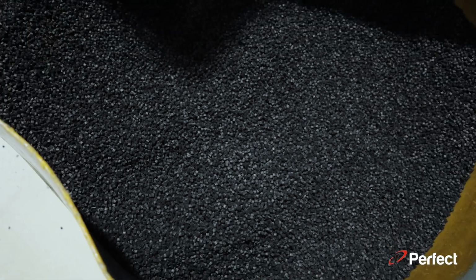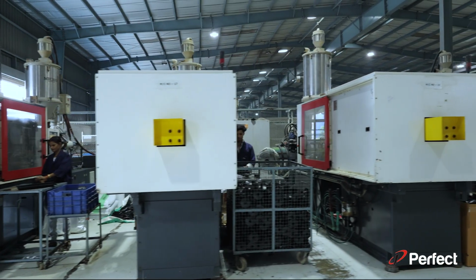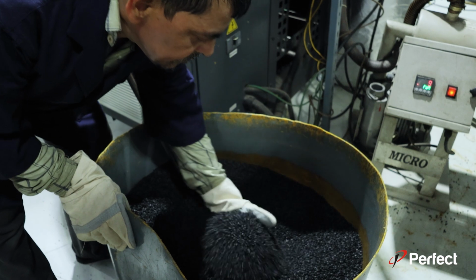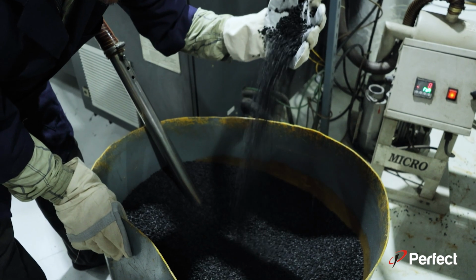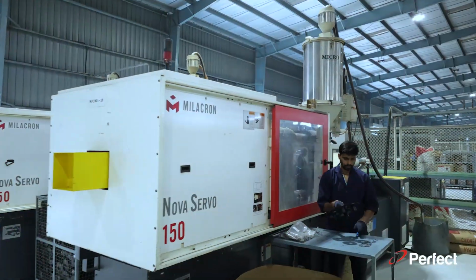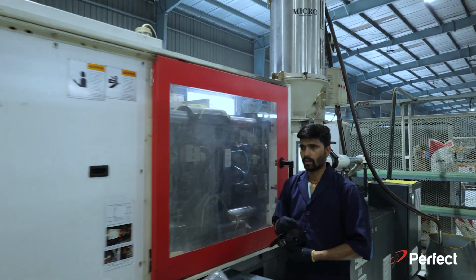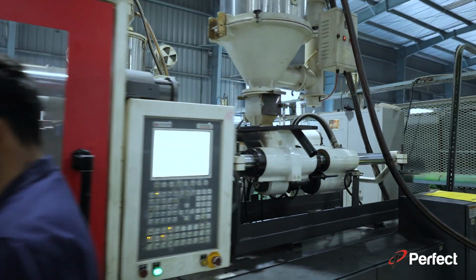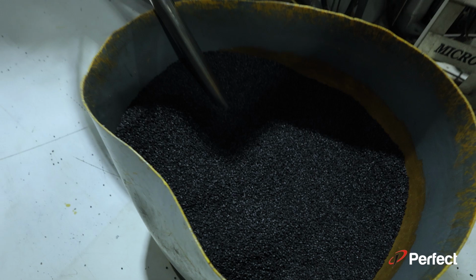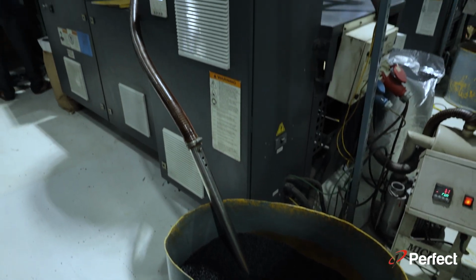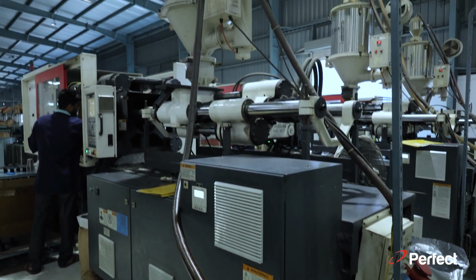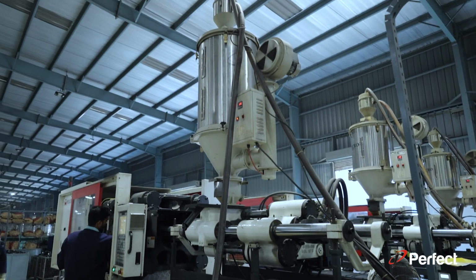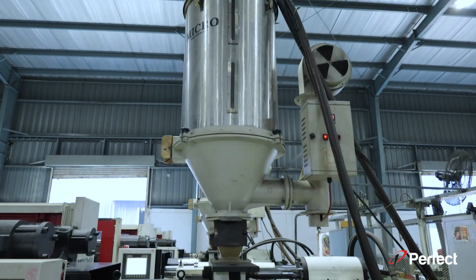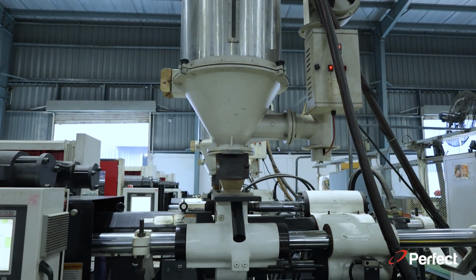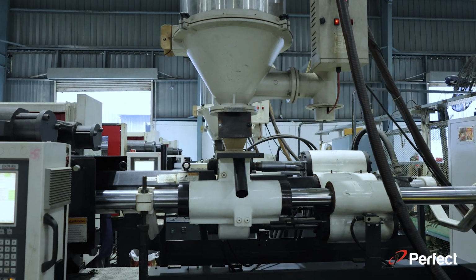Injection molding. The raw material used for molding various plastic components primarily consists of nylon 6 granules, reinforced with 30% glass fiber. This nylon composite is processed using high-precision plastic molding machines. The process begins by transferring the nylon granules into a hopper, where they undergo a preheating cycle to eliminate any moisture content. This drying phase typically lasts for a minimum of 2 hours.